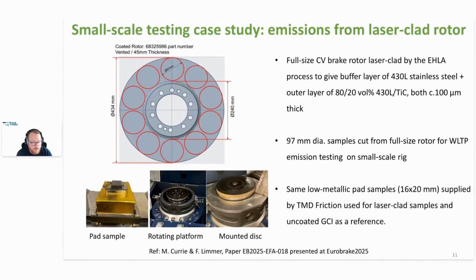The starting point for this case study was a full-sized CV brake disc, which had been laser clad to give a 2-layer coating consisting of roughly 100 microns thick pure 430L stainless steel buffer layer, and then a composite top layer of 430L plus titanium carbide particles.